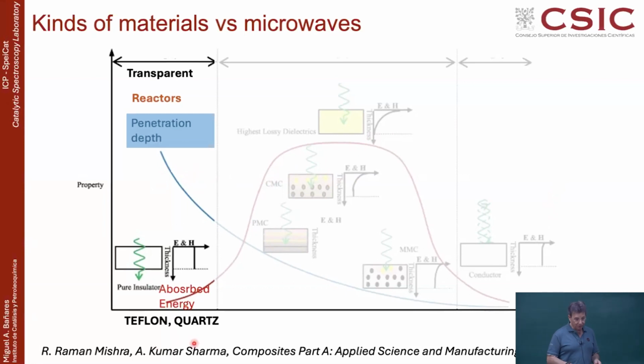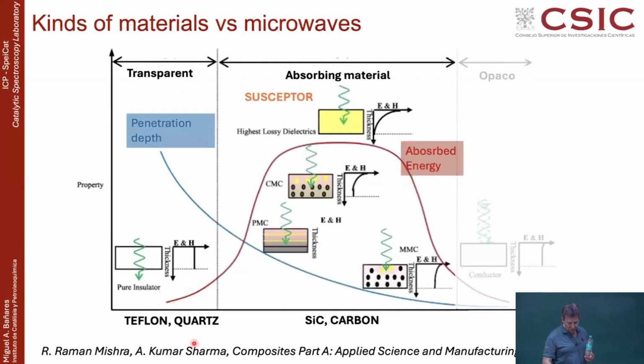Well, that's good because if you make a reactor, the reactor can be made of Teflon, can be made of quartz, and you put the catalyst here, and then the gas or the flow goes through it. And a Teflon tubing or a quartz tubing is convenient. Glass tubing is convenient. Then you have another kind of material, absorbent material, the one you want to get hot. That will be inside, it will be the catalyst. It's a material that will absorb energy, and of course the penetration will be lower because it is absorbing the microwave radiation, so microwave will not penetrate too much because it is being already taken and absorbed by the material, but the material is getting hot. So basically this is the absorbing material, and this is the key element.